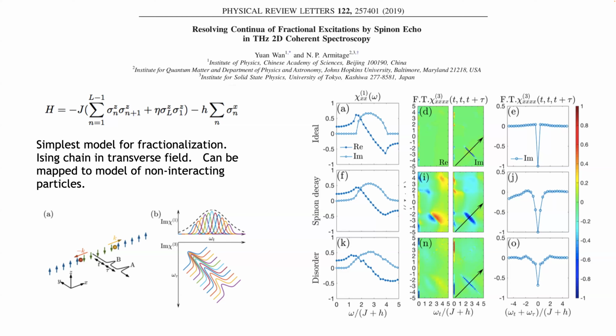So Ising spins interacting with each other with a nearest neighbor interaction, and then a transverse field where you can tune it through a quantum critical point. The linear response famously is this kind of broad blob feature, but the nonlinear response in the 2D plane has this sharp streak. And that sharp streak, a cut through the anti-diagonal direction, is a signature of the inverse lifetime. And through experiments like this, we believe that we can measure the differences between, let's say, strong disorder and strong interactions, or measure lifetimes of the two spinon states, if you will.